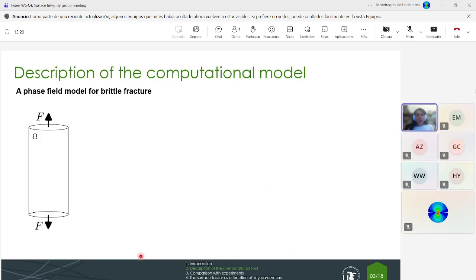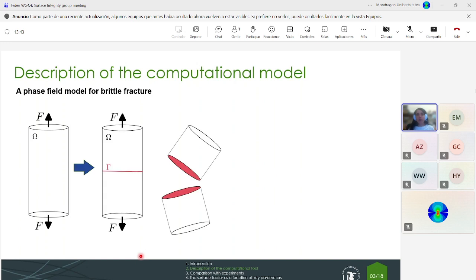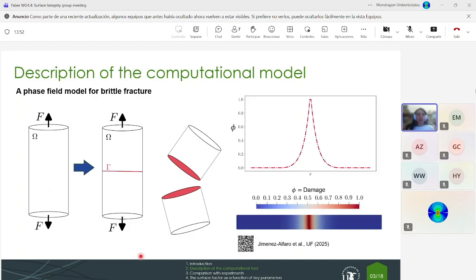So before going into details about the results and also how to build a rough mesh, I would like to explain some details about the phase field model. And for that, imagine we have a bar in tension. At a certain moment, the load is so high that then a crack appears. And this crack can be considered a discontinuity in the material. So the basic idea of phase field is to substitute this discontinuity using a phase field variable that goes from 0 to 1. So we change this discontinuity to a smooth transition.